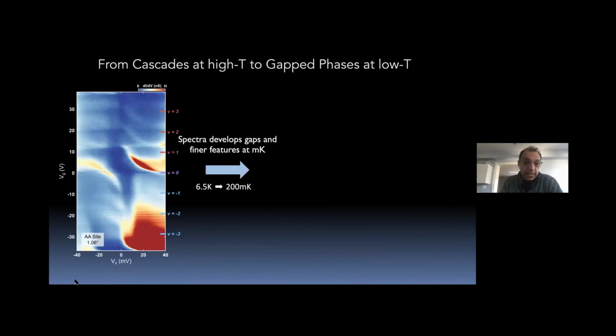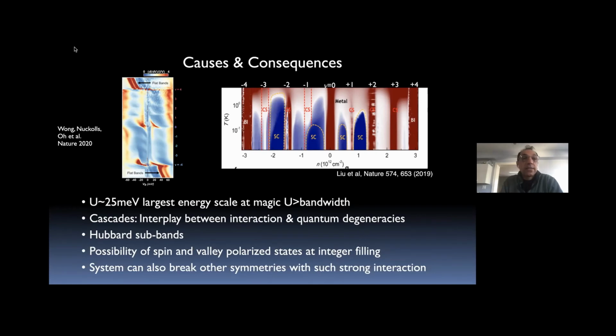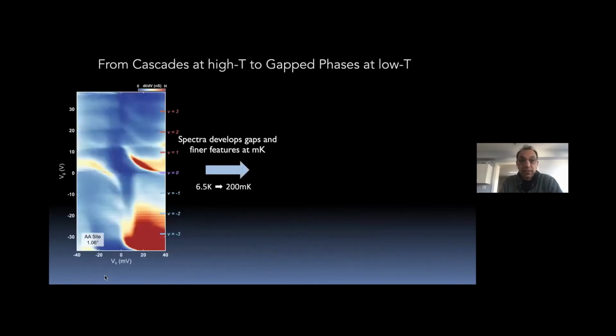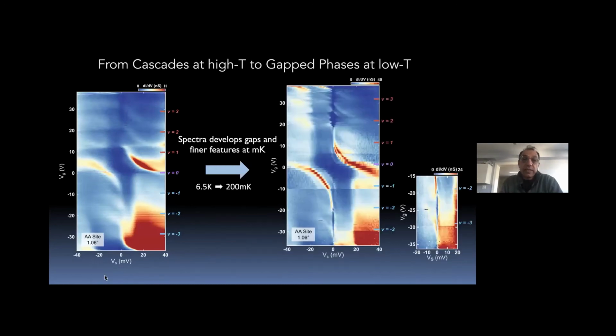So incidentally, these experiments I showed you just now were done at 6 Kelvin. And this is sort of like the normal state property of the system before we get into the correlated insulating phases or the superconducting phases. Now, let me just say that when you take the samples to like 10 millikelvin, with electron temperatures of like 200 millikelvin, you begin to see gaps develop, which are associated with the correlated insulating and superconducting phases.